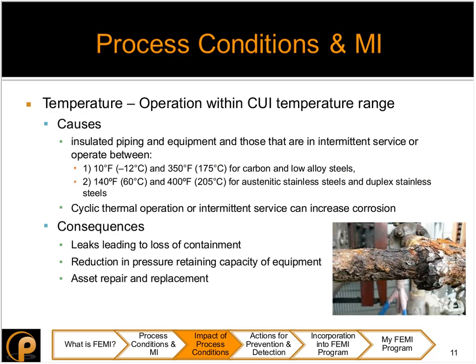The next condition is temperature. Specifically operating in the corrosion under insulation, or CUI, range. CUI is a very common and very difficult to detect damage mechanism that you find commonly in most oil and gas facilities. CUI can be very expensive to mitigate and very difficult to detect because most of it is under the insulation, and you might have to use detailed techniques, which I will describe later, to detect CUI. If you don't have a program in place, you can probably only detect it when you have leaks or failures.